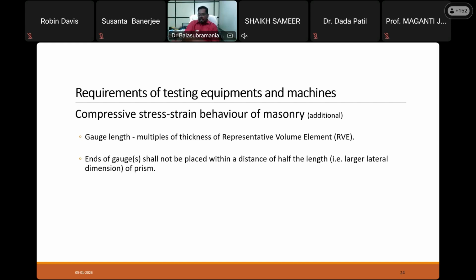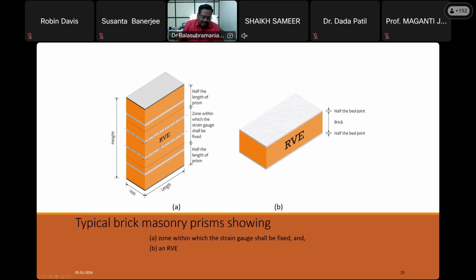Have a look at this diagram. See, in the case of brick masonry, we have a brick and then there is a joint and then another brick, isn't it? So look at the right figure. We have a half thickness of the bed joint, and then there is a brick and a half thickness bed joint below. So this is one representative volume element, because if we repeat this representative volume element periodically one above the other, we can obtain this specimen, right? This is the periodicity element, that is the representative volume element.